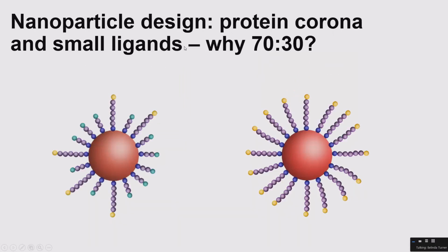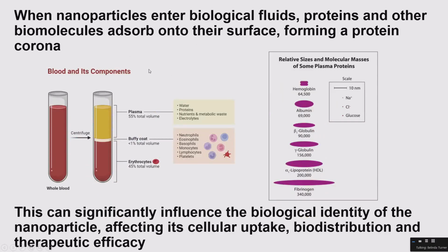So then you may be wondering why we're using this 70 to 30 ratio of the short and long. And this is because the protein corona makes it notoriously difficult for small ligands to bind in vivo, because when nanoparticles enter biological fluids, proteins and other biomolecules adsorb onto their surface, forming a protein corona. It has nothing to do with coronavirus. It's just basically if you imagine a particle with a cloud of proteins surrounding the particle floating around, it can inhibit the binding because those proteins obscure the targeting ligands. So this can significantly influence the biological identity of the nanoparticle, affecting its cellular uptake, biodistribution, and therapeutic efficacy. It can virtually render it just not usable.